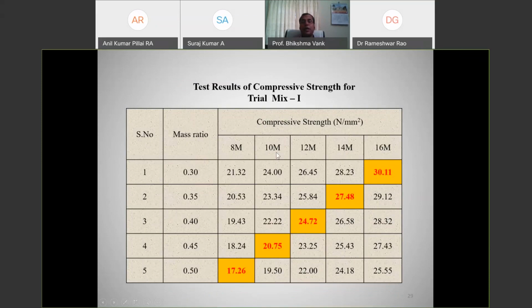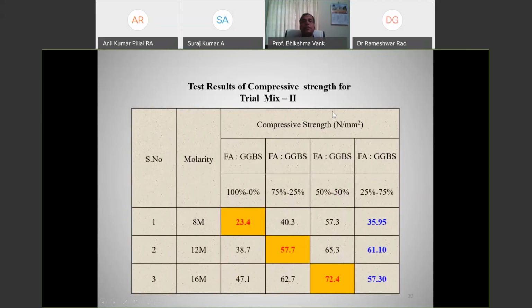But one thing is, if molarity increases, your cost also increases. Therefore, better we should look at the lower molarity. That is better in the research actually. If your molarity is increasing, your cost is also increasing. Compressive strength you get more, but cost is also more. Therefore, results of compressive strength for trial mix for 8 molarity, 12 molarity, 16 molarity, we got 23, 57, 72.